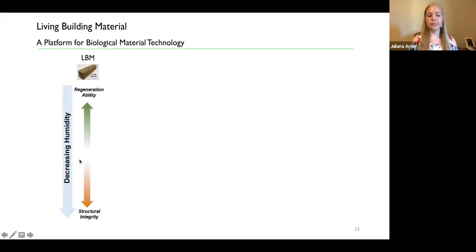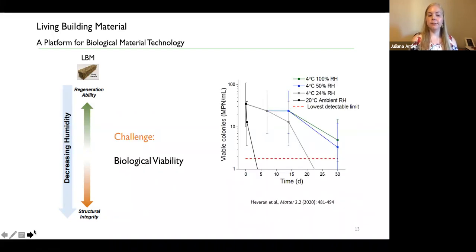So we know from our previously published studies that if we have more humidity in the bricks, we have a higher amount of cells alive. But if we want better structural integrity and we need to decrease the humidity, we face this challenge of bacterial viability in the living biomaterials, and we want to keep them alive because of the idea of living building materials. As you can see in this graph, if we follow the number of viable colonies in the bricks through time, if we keep the cells under low temperature and high humidity, the cells can survive even for up to 30 days. However, to increase the mechanical properties, if you want to dry them more, for example, using ambient relative humidity, like a lower relative humidity and higher temperature, the cells cannot survive. So that was one of the challenges for the project.